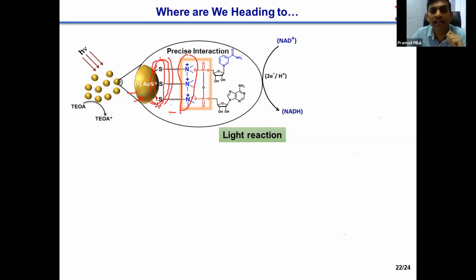It is well known that thiols have more affinity to gold when compared to amine, so that kind of place exchange will be very easy. But if you want to functionalize multiple ligands, as I was talking to Professor Pradeep, that is where the challenge is. And we were able to optimize this with two types of ligands, where we play with the solubility of the ligand.